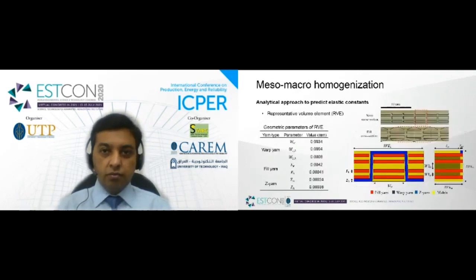So now, macro homogenization requires details of the representative volume element, or RVE. The RVE is the representative unit cell of the 3D fabric at macro scale. The geometric parameters of the RVE were determined using digital images obtained from a digital microscope, which are summarized in the table. These geometric parameters are used to evaluate the volume proportion of each constituent in the RVE.